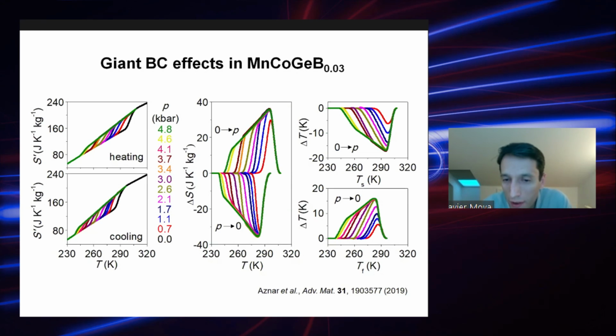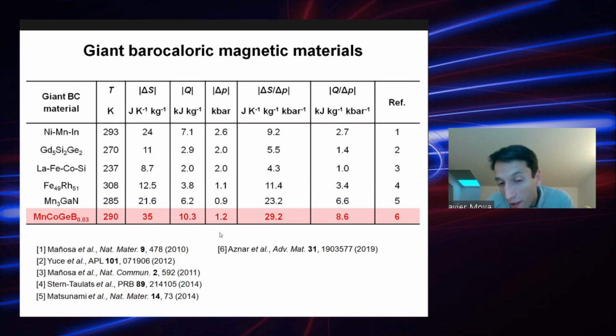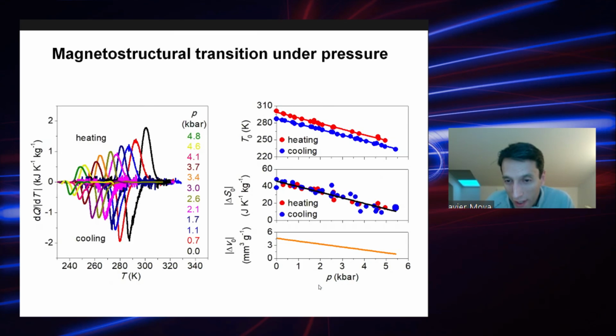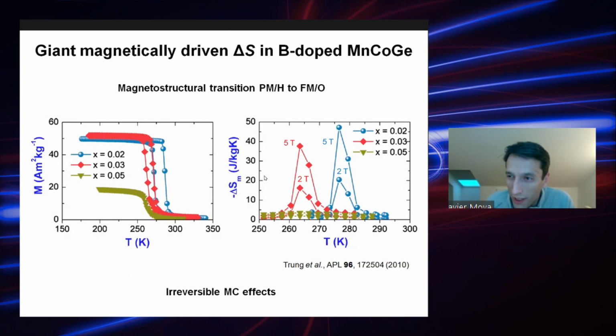And then what you can do is you can do the calculations of caloric effects, and this is a summary of the results. And you can see that because the volume change is so large in this material, the transition shifts a lot with pressure. So you can get very large barocaloric effects under relatively small pressures, and they are reversible at low pressure. So you can then compare these to the existing materials that I show you. So you can see that the performance is pretty good. And importantly, the message is that you can take sometimes magnetocaloric materials that are not reversible applying magnetic field, because the shift with magnetic field of position is not that large, and then use pressure instead.